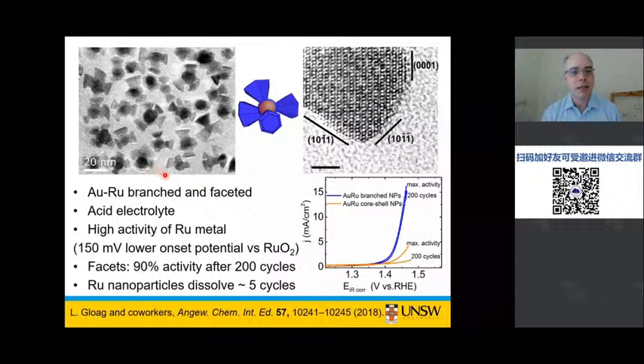So you can see that for each of the particles, we have a dark core. So each of the particles actually has a gold core in the center. And then off the gold core, we have these kind of wedge-shaped ruthenium arms that grow off this central gold core. So we've got all these wedge-shaped arms growing off this dark center. So actually we end up with particles that look a little bit like this. So you have a gold core and then these faceted arms.